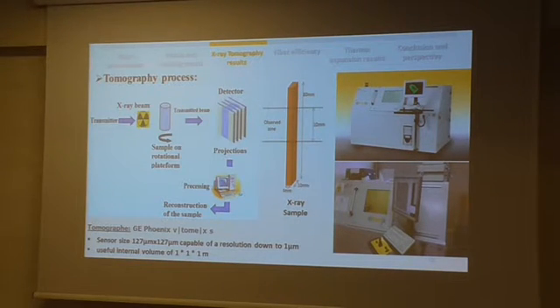For further understanding of this composite, we used the X-ray tomography technique. This technique allows us not only to see the fiber distribution, but also to calculate the fiber fraction and void fraction in the sample, and also to measure the fiber length and diameter in the sample. The sample used for this technique is the same used in the bending tests, and the resolution used here is between 5 and 6 microns depending on the mixture.